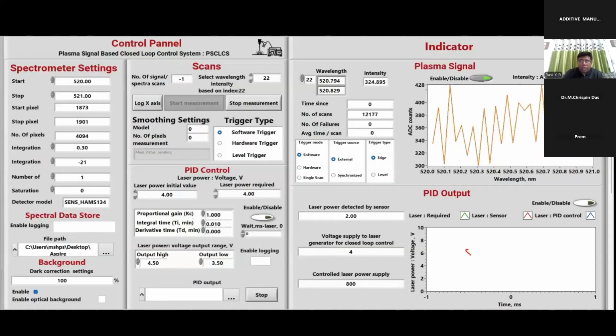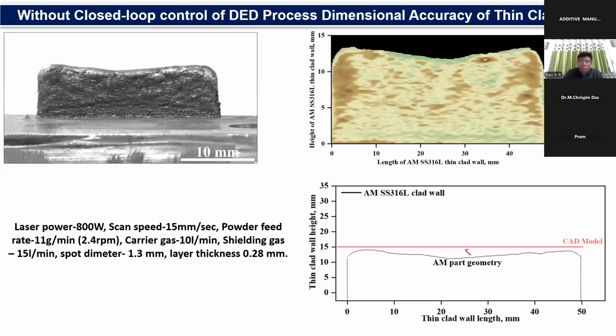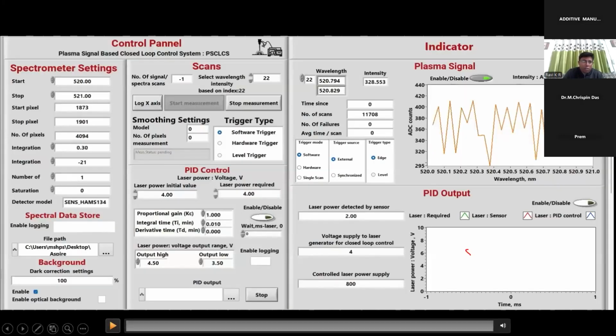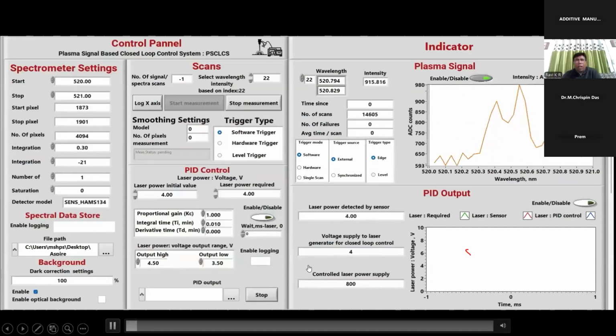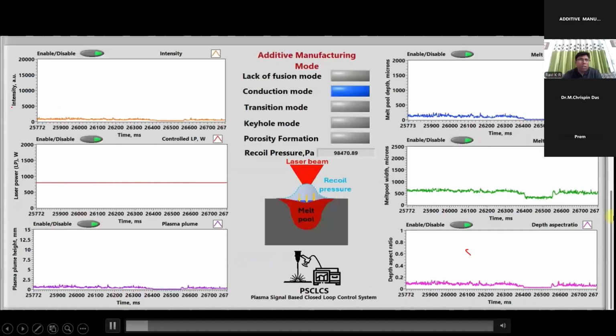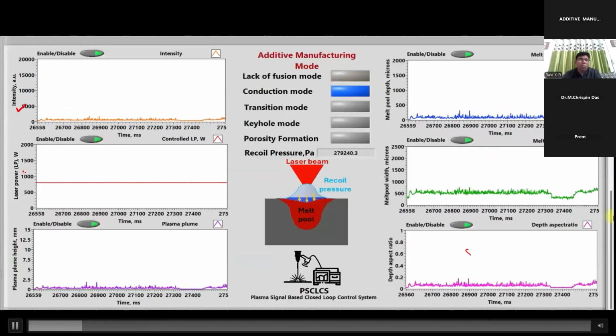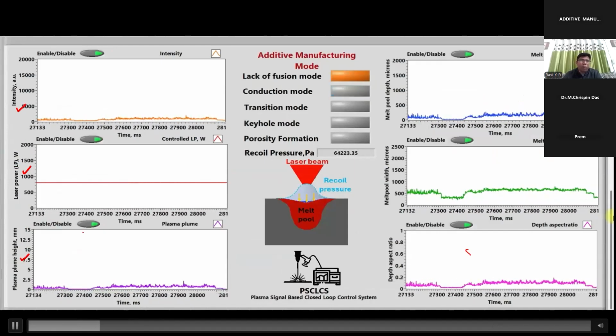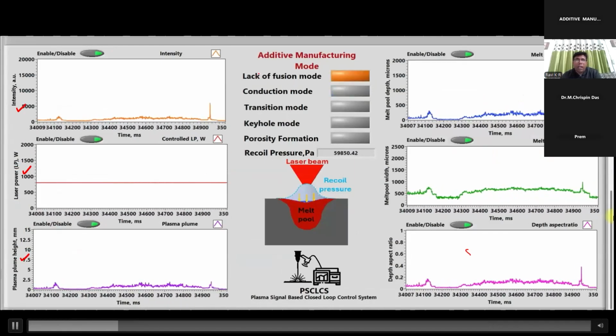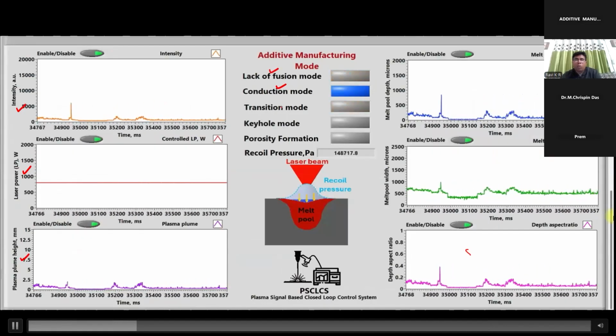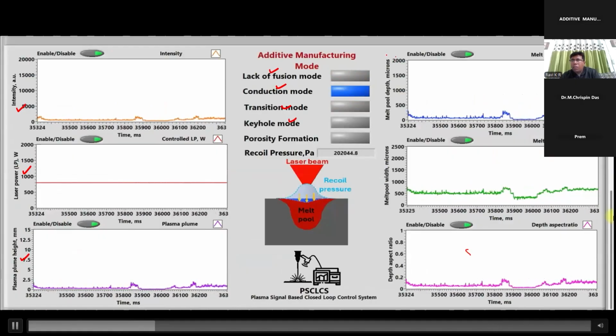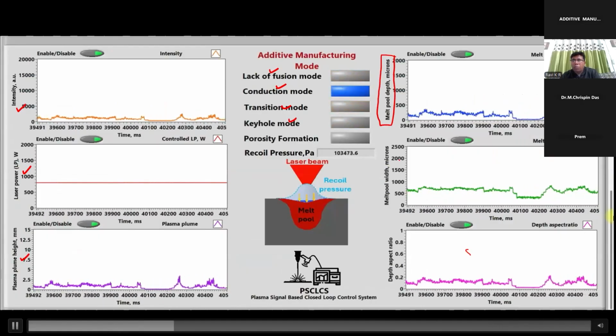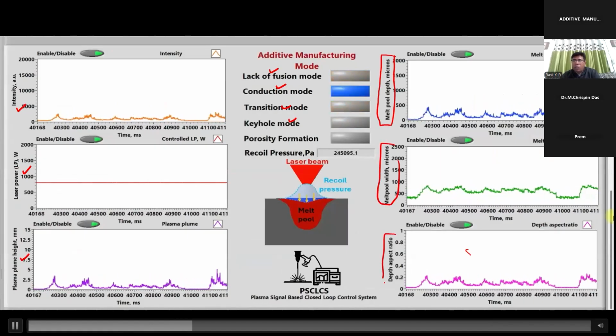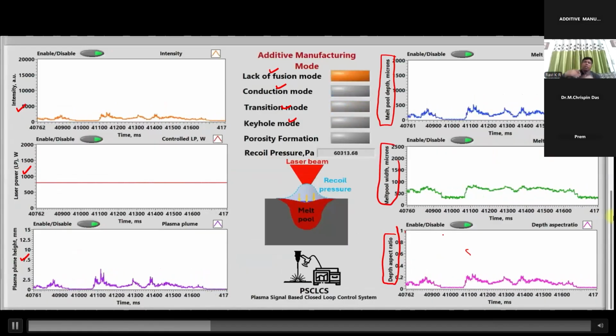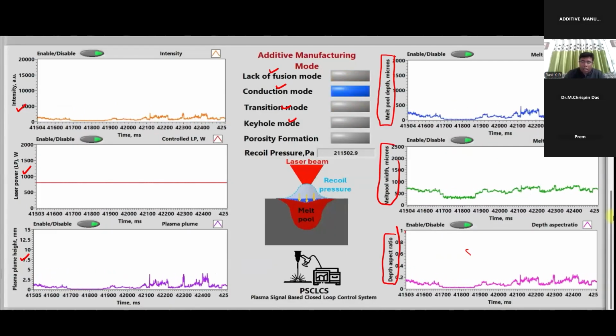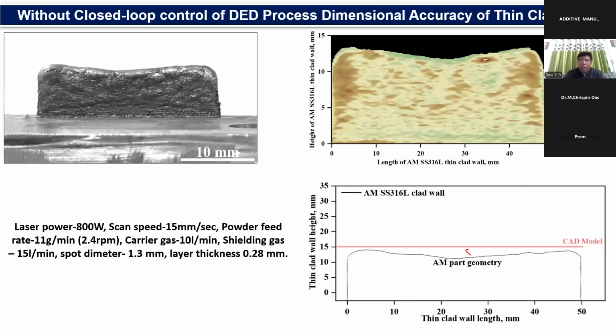In addition, the software we have created will give you all the features required for printing, which one can see in the dashboard. It gives you an idea about what laser intensity and power we are using, and what plasma plume height we are getting. It shows whether we are working in lack of fusion mode, conduction mode, transition mode or keyhole mode. We get live details of melt pool depth, melt pool width, and depth aspect ratio. All these things are important, and give you an idea about whether you are in an appropriate printing condition or not. So now you can see the quantitative difference.